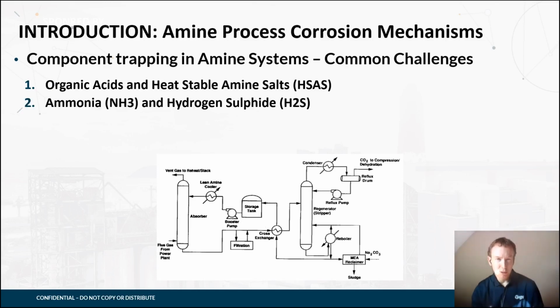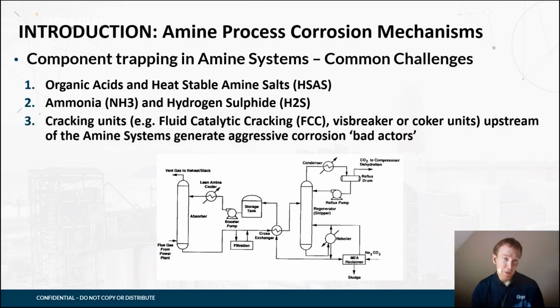We've got our ammonia and hydrogen sulfide, which can accumulate in the top of the column, creating this aggressive concentration and corrosive environment. And then upstream of the amine system, if we have cracking systems, then we can introduce hydrogen cyanide, which can retard the generation of protective oxide layers and barriers and lead to cracking potentially in the units. So these bad actors are there in the process.